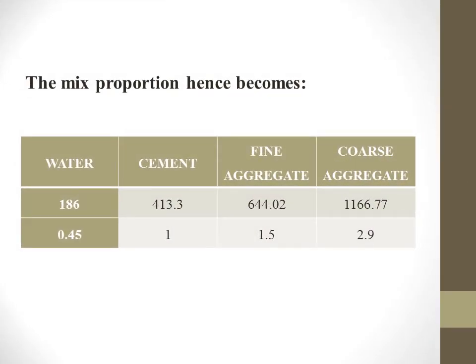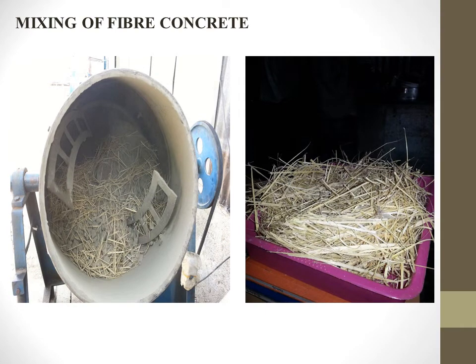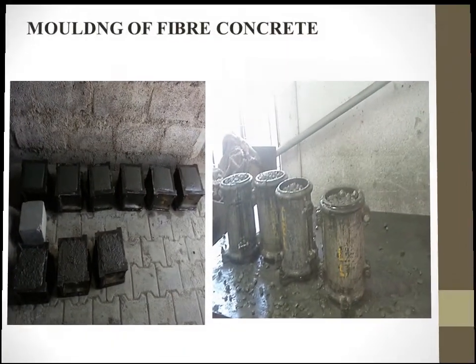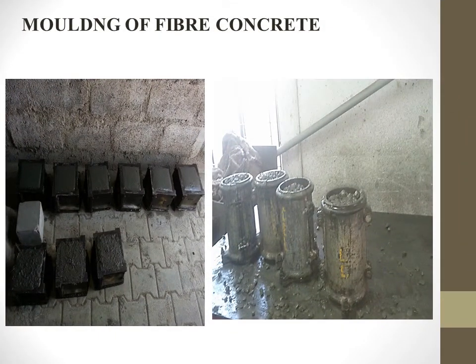Now we had come to the final part of our design procedure, that is the mix proportion was successfully found out, and the proportion was 1 part of cement with 1.5 parts of fine aggregate with 2.9 parts of coarse aggregate along with 0.45 parts of water. As you can see, we had used a mixer for mixing of fiber concrete. Cubes were casted and cylinders were also casted.